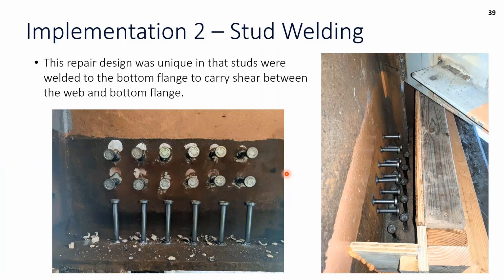Looking at the stud welding in the field, this is where you can really see those 2 main differences in the standard layouts. In the first layout, this is when we had not as significant of a length of corrosion damage along that interface between the web and bottom flange. We only had 1 row of flange studs, and where we had a longer length of corrosion, we had those 2 rows of flange studs.